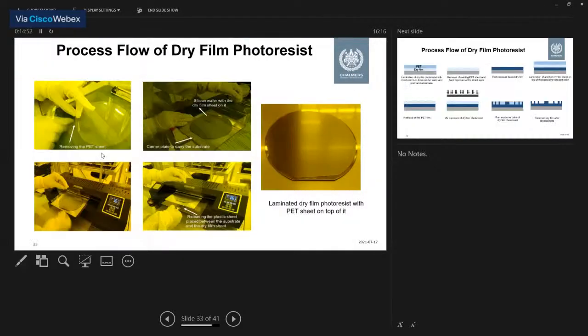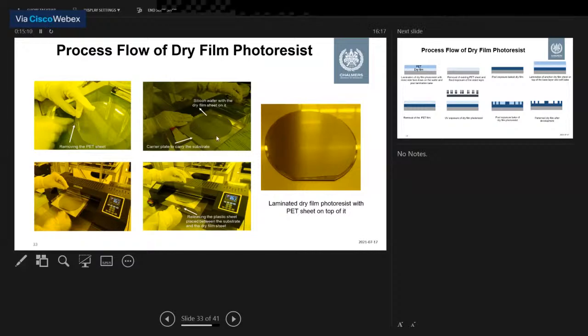So this is the process flow of dry film photoresist. Dry film photoresist actually comes in paste combined with two plastic sheets. So we first need to remove the plastic sheet, and we need a substrate. We put the uncovered part on the substrate and then laminate through a normal office laminator. And here you can see a laminated dry film photoresist, the PET sheet on top of it, and you can see that it is very flat, and it's laminated very perfectly.